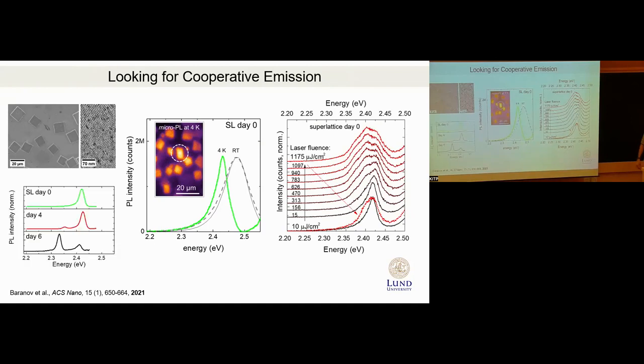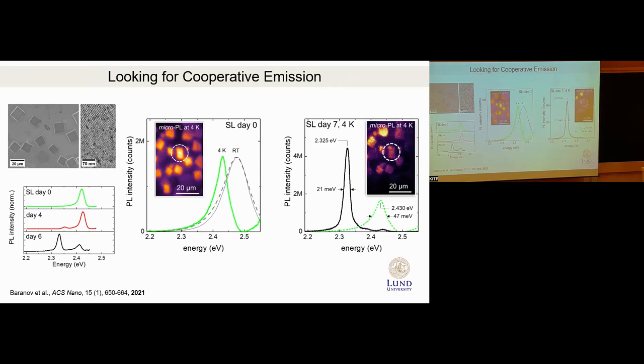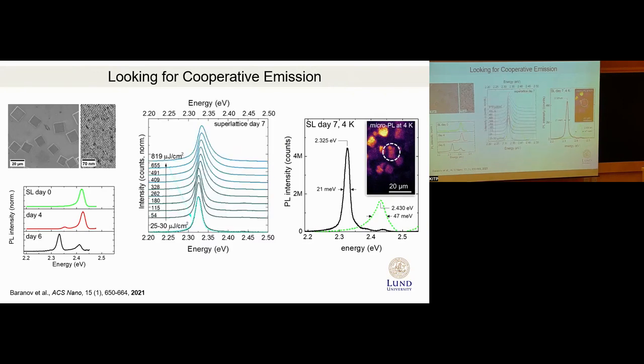However, what we noticed is that when you keep the superlattices at room temperature, over time the lower energy peak starts growing by itself, which was surprising. So we looked at the same superlattice 7 days later. The experiments were done at 4 Kelvin, but in between it was kept at room temperature. And what we saw is that after 7 days, on its own, the sample changed, forming this intense low energy peak. Is this superfluorescence? We don't know.